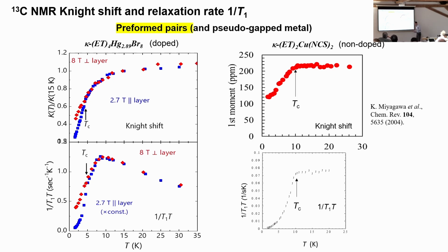So I think that this material has a pseudogap, a very small pseudogap, which may open in a part of the Fermi surface, like underdoped cuprates, but no competing orders. It still remains incoherent, I think. And the preformed pairs occur below 8 Kelvin, roughly twice the TC here. And then the decrease of the Knight shift is accelerated. So that's one plausible scenario to explain these materials.